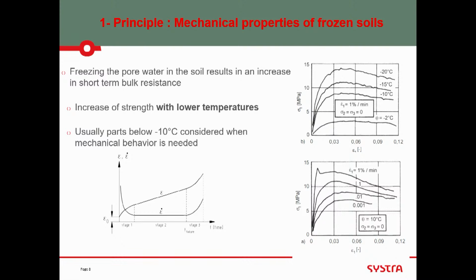Now, let's see what happens when we load a sample with different strain rates. In fact, now you are pushing the sample, so you are dictating the strain as a function of time, and you are crushing the sample. On the horizontal axis, this is the strain. On the vertical axis, this is the vertical stress applied to the sample, no confinement. This is still the UCS here. The sample has a temperature of -10 degrees. These are not the same sample.